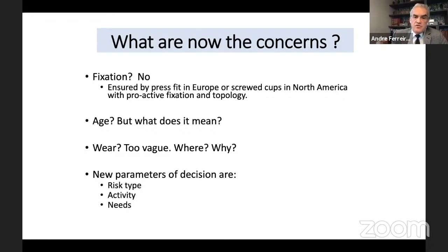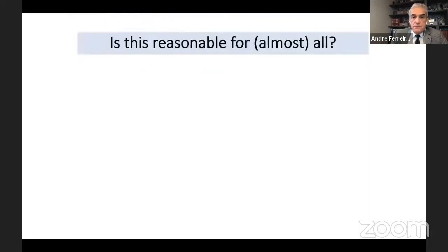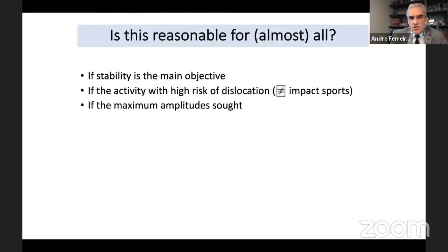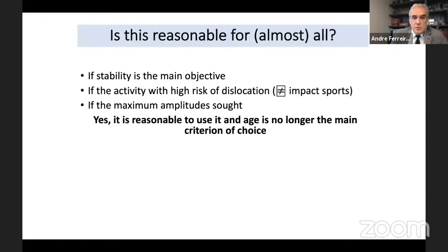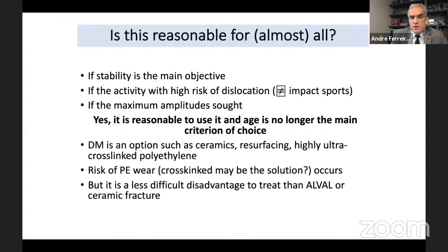So the new parameters of decision are risk type, activity, and needs of the patient. And if you have a patient at very high risk of dislocation, because he performs some sports with a very high risk of dislocation, because he does trekking in the mountains alone, because his work needs a very high range of motion, probably dual mobility is better. So is this reasonable for almost all? Yes, if stability is the main objective, if the activity has a high risk of dislocation, and if maximum amplitudes are sought. Yes, it is reasonable to use it, and age is no longer the main criterion of choice.